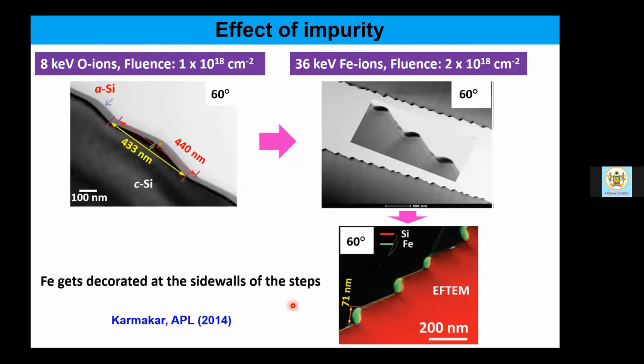See, this is oxygen ion induced pattern formation. This is 8 keV oxygen. This is the effect of impurity, and this is iron, 36 keV iron ions at 60 degree. Both in case of silicon.